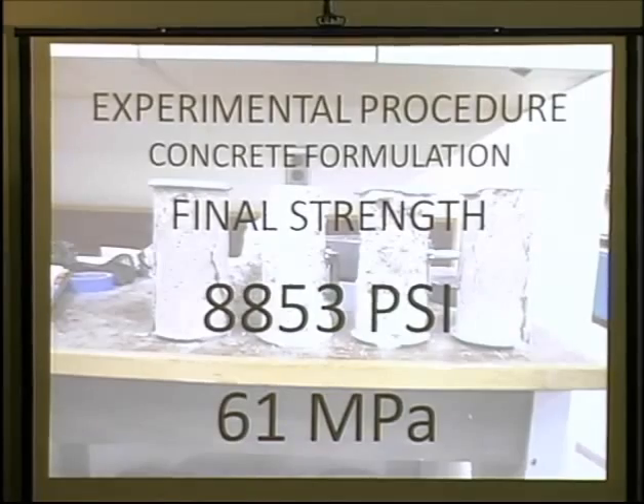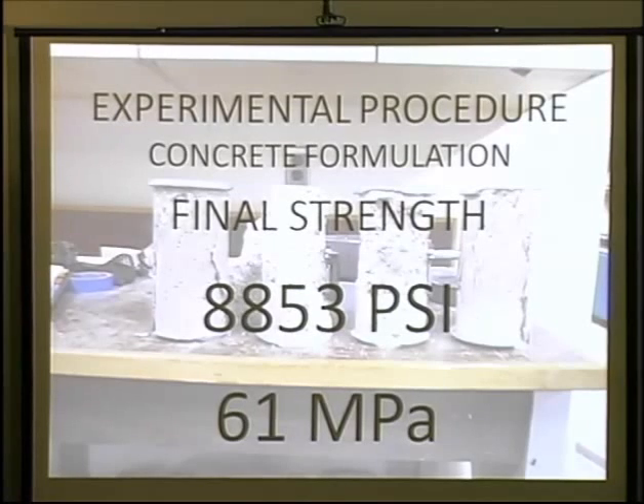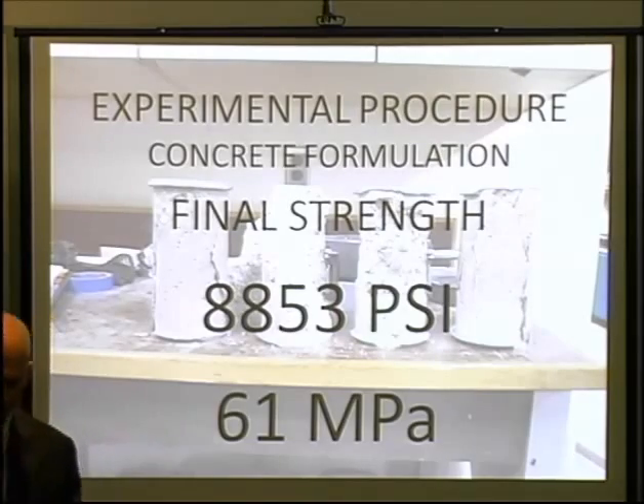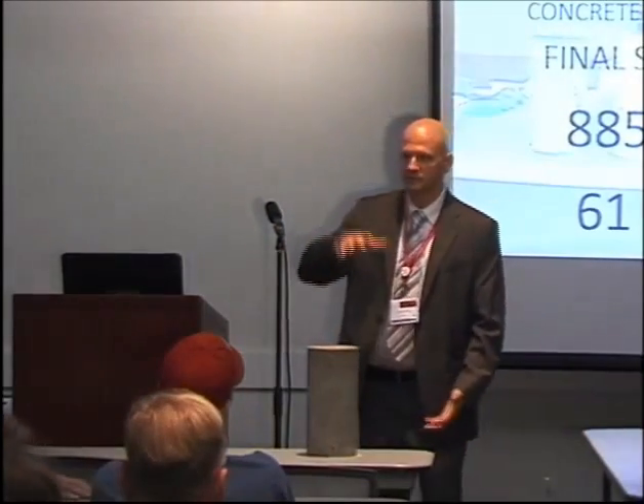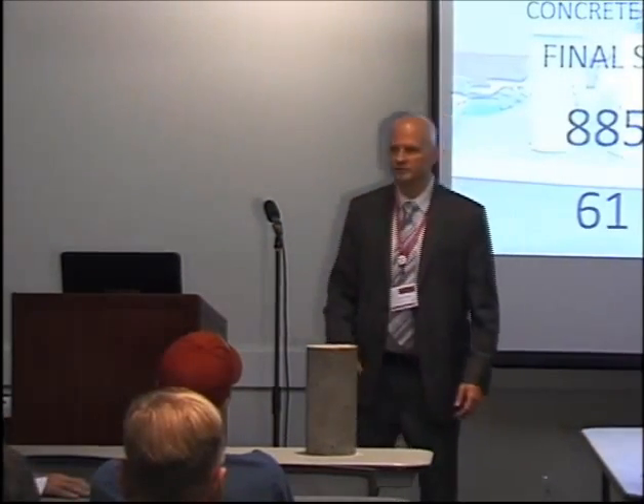And testing it after 1 week of curing, got a final compressive strength of 8,853 pounds per square inch of force. Should explain compression testing is just crushing. We make concrete cylinders like I have up here and put it in a compression tester and just crush it and apply pressure until it fails.